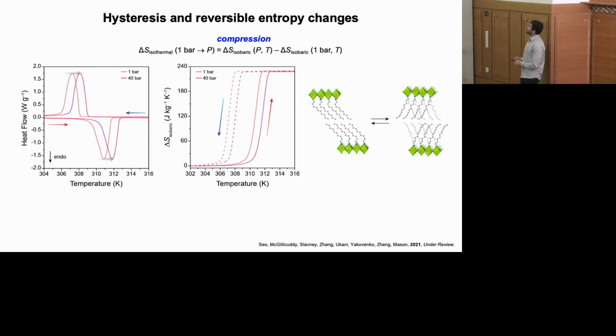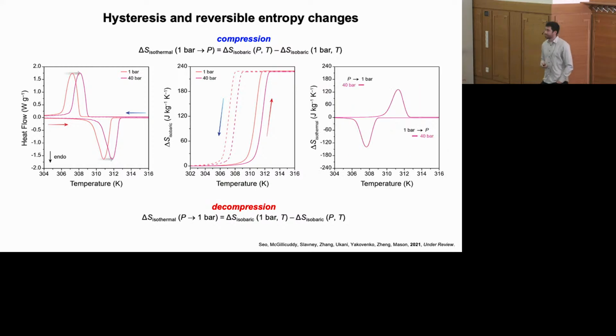And this is where the thermal hysteresis associated with the phase transition becomes really important. So when we're thinking about evaluating the entropy change associated with compressing or applying pressure, the data that's most relevant corresponds to the DSC data from cooling curves. Because cooling is what's inducing this transition to the more ordered state, just like compression. Alternatively, when we're thinking about removing pressure from our material, that's inducing the transition to the more expanded, disordered phase of our material. So it's going to be analogous to the transition that's induced by heating. So there we care more about the data from heating.